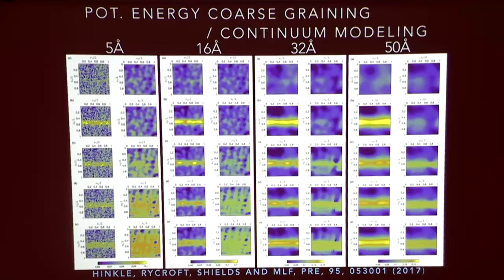You can clearly see that if we coarse grain too finely, there are all these fluctuations in the potential energy field and hence the effective temperature field, and so we don't end up getting the localization that we see in the MD. Whereas if we coarse grain above 32 angstroms, up to 50 angstroms, then we start seeing much more similar behavior between the MD and the continuum simulation.